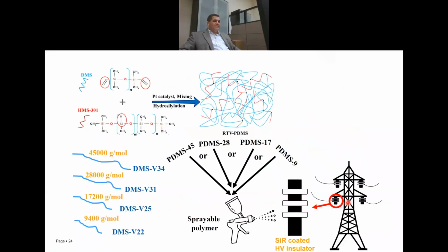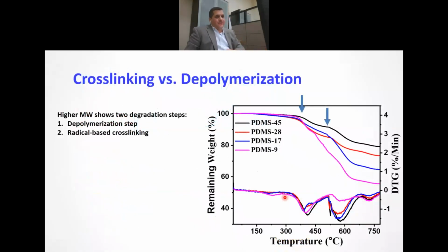So yeah, it is done through spraying, and we use the ceramic tiles, which is typically accepted. And for those coatings, we started to look at the material science part, the material characterization part. This is typical TGA. TGA is very important in this kind of application because the thermal stability is very important. When an electrical arc happens, it mainly creates heat, and the dissipation of heat is very important. So the thermal conductivity, or the thermal stability of the material, is very, very important.